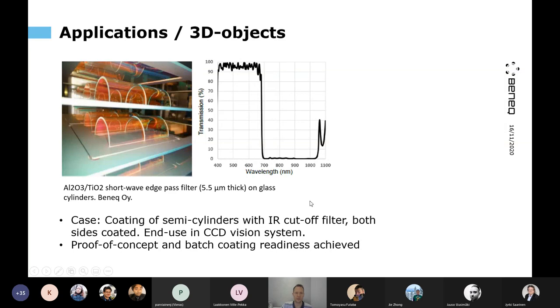So this is an infrared cutoff filter, and this is from an actual case where we used this. This glass was used as a part of an enclosure for a camera system. So the purpose was to prevent infrared light going in. And we managed to make very uniform coatings on these, and use a relatively large batch size also to coat this. So again, another example that only ALD can do.